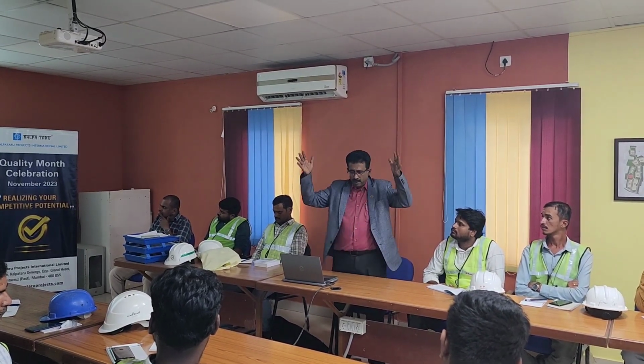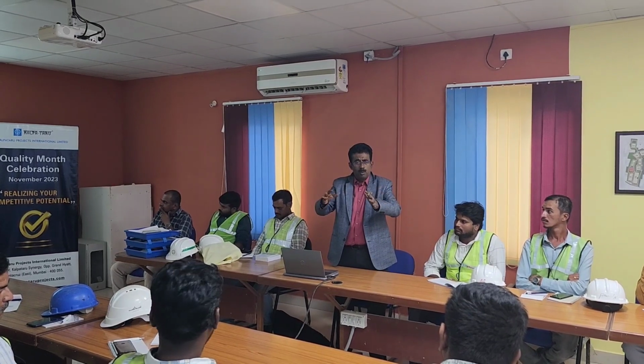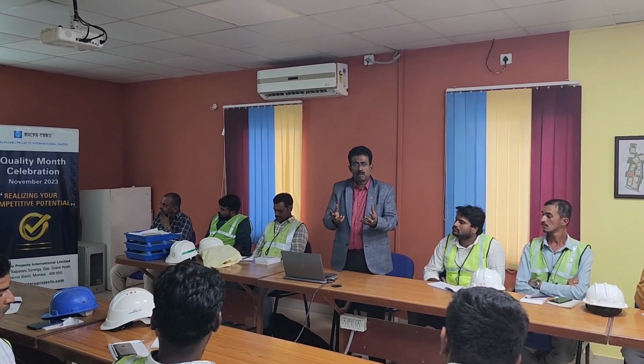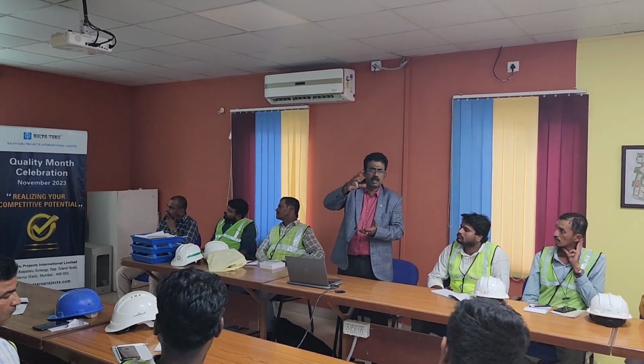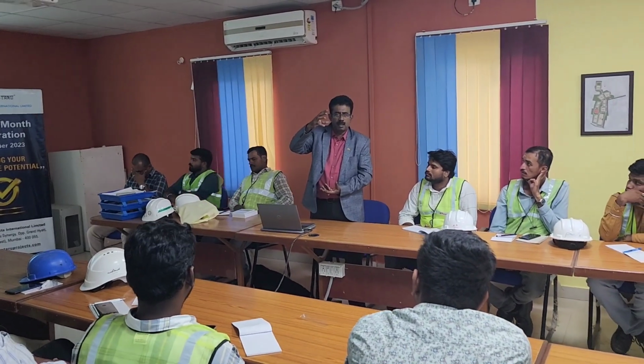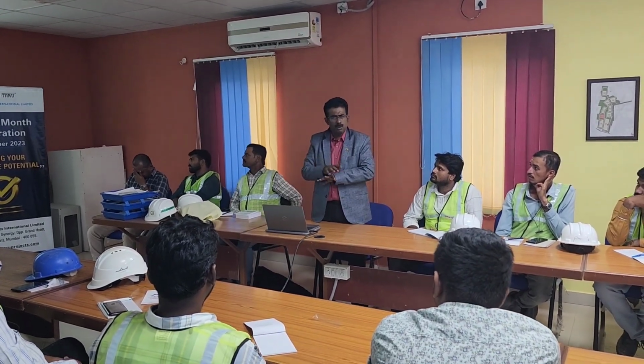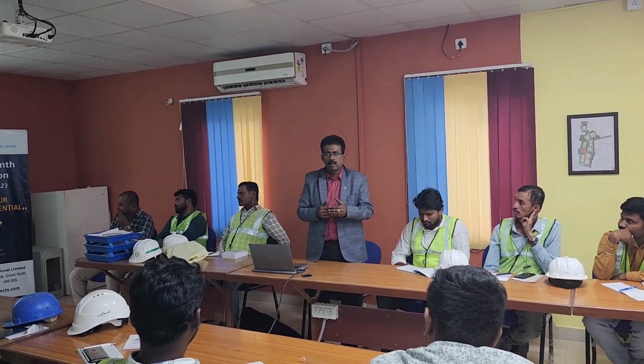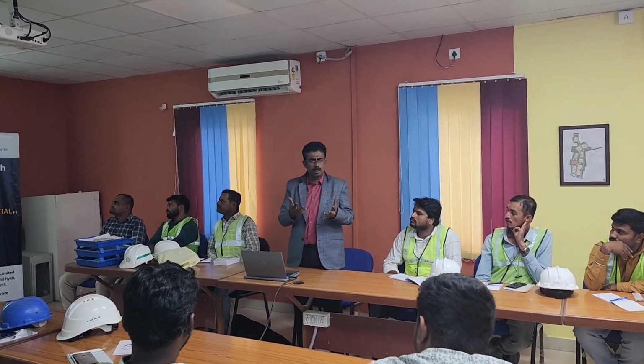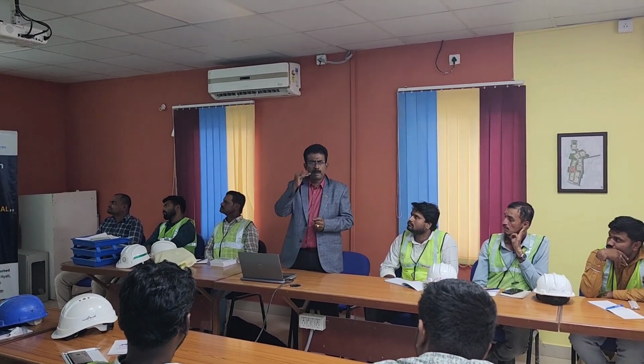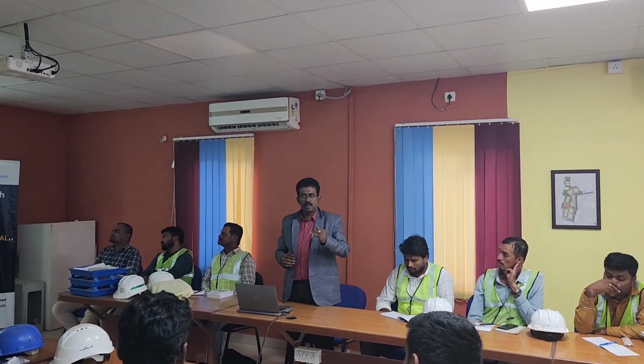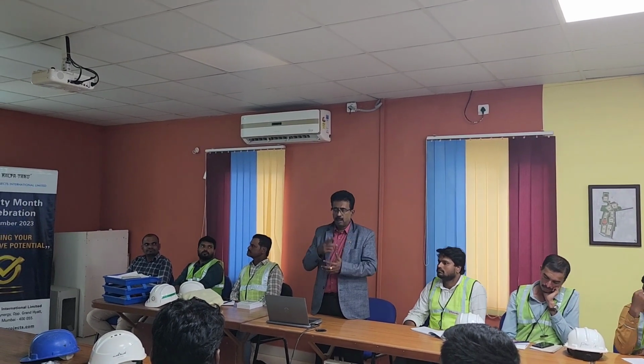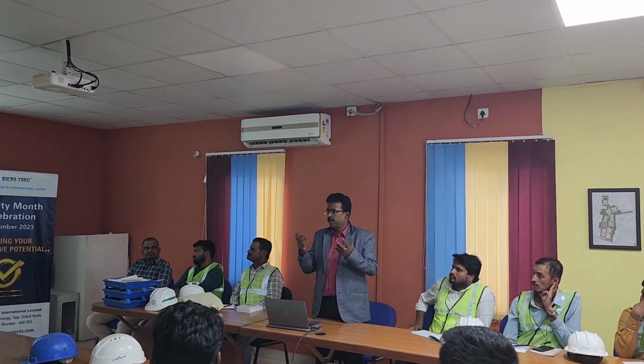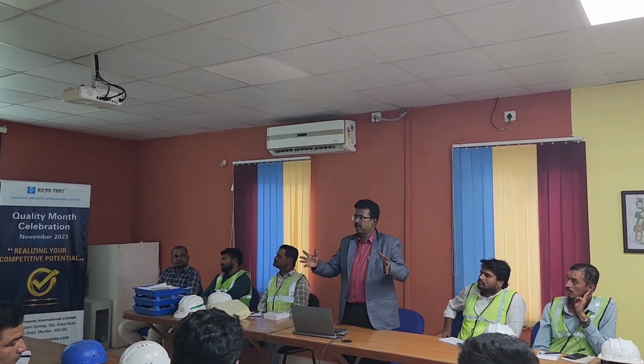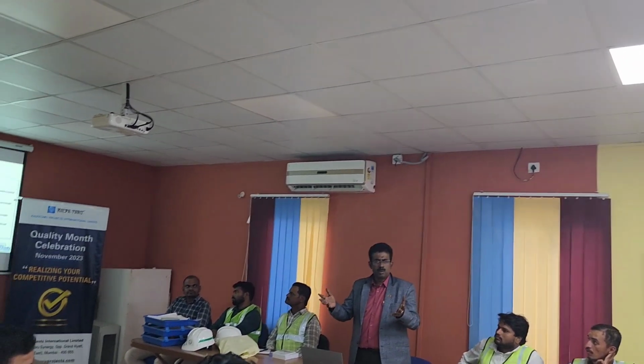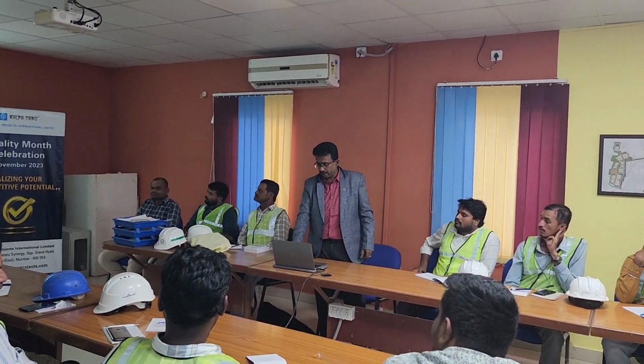It cannot dissipate, because it is confined in the soil. So it will generate a lot of heat. The surface will have, let us say, 35 degrees centigrade, and here 80 degrees centigrade. The gradient between these two leads to a lot of cracking. To avoid that, we have to use a higher percentage of GGBS, up to 60%, 65%, 70%. The code permits up to 70%. We can use it to cut down the heat generation. Many projects are now adopting rafts of 2 meter, 3 meter, 6 meter with up to 60% GGBS. I'm going to show you the slide also.